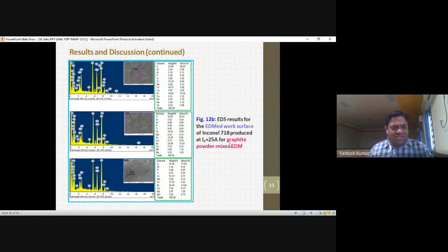Apart from this localized phenomenon, it could also be concluded that the graphite powder mixed EDM results in less carbon migration onto your machined surface, as compared to conventional EDM. So this tends to reduce the probability of formation of hard carbide particles at the machined surface, and thus reduces the severity of cracking also.